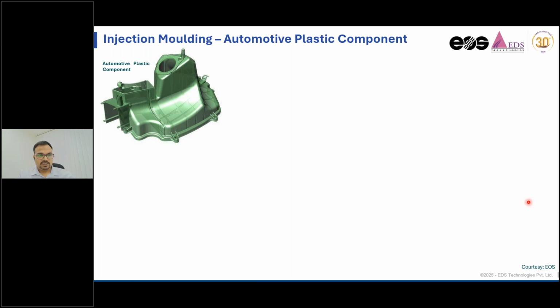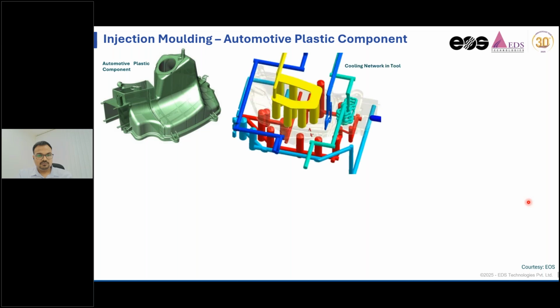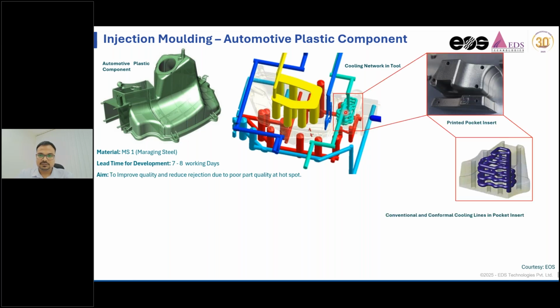So this is one automotive plastic component we have taken, and this is the cooling network in the mold. This is the area where the problem was actually lying. There was a critical cooling condition, and the part was getting rejected due to a hotspot generating on this. So in order to improve the cooling, calibrate the cooling, the insert was replaced,